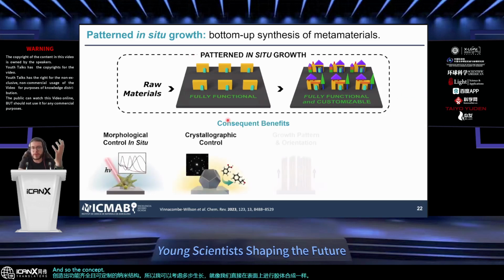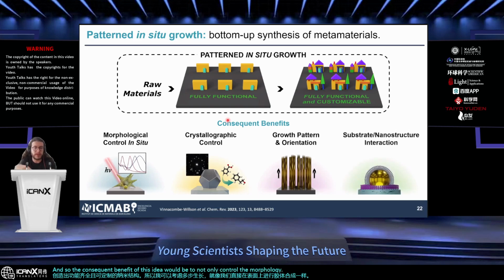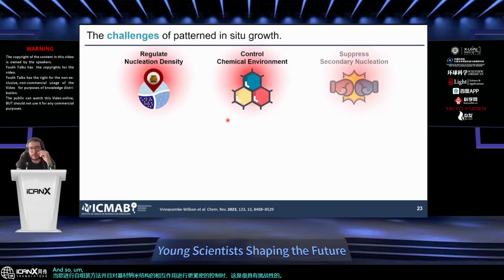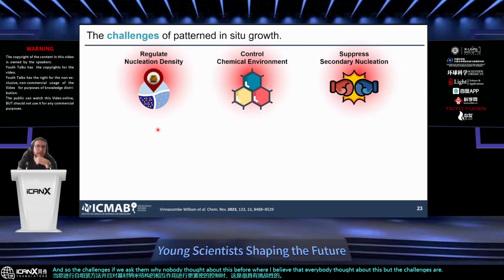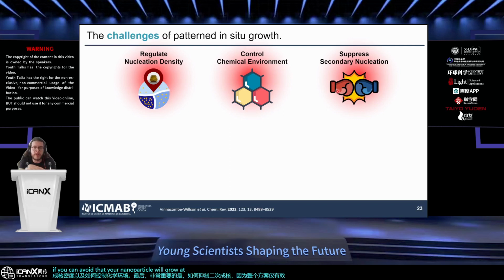And so the consequent benefit of this idea would be to not only control the morphology and crystallography in situ, but also to control the pattern orientation. So how my nanoparticle is growing compared to the substrate, which is something quite challenging to do with a self-assembly approach, and also to have a much more intimate control over the substrate-nanostructure interaction. And so the challenge is, if we ask why nobody thought about this before, I believe that everybody thought about this, but the challenges are how to regulate the nucleation density and how to control the chemical environment. And also, and finally, very importantly, how to suppress secondary nucleation, because this whole scheme works only if you can avoid that your nanoparticle will grow at the same time on the substrate and in solution.